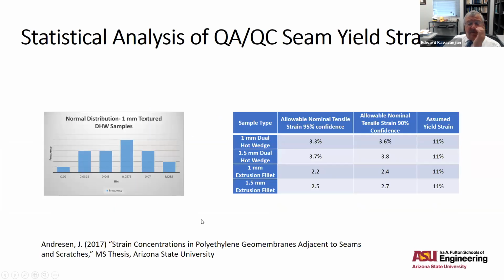So one of the things we did with this data: we had over 100 seam specimens from construction quality assurance that were provided to us by two consultants who did a lot of CQA work for geomembranes. These were excess seams that they had. And so we failed those seams. We grabbed those seams, stretched them, and failed them in tension. We plotted up the results of the tensile strains on the seams. It looked pretty much like a normal distribution to us.